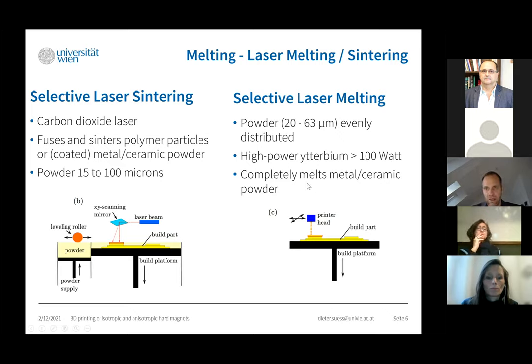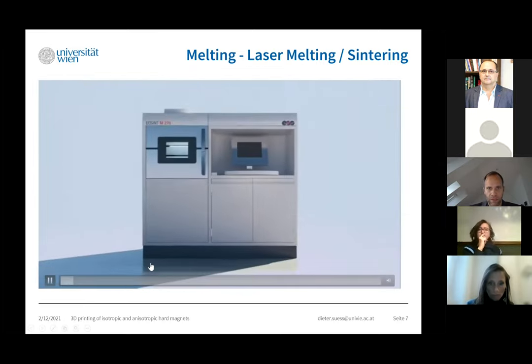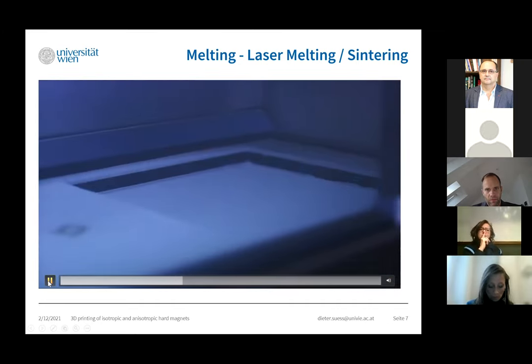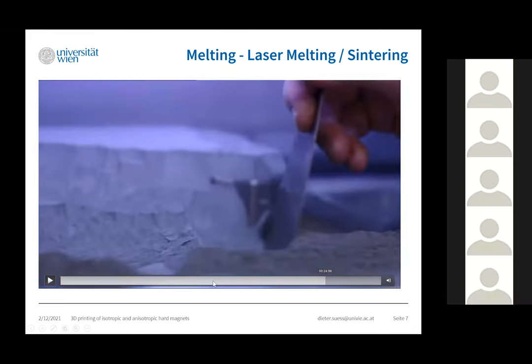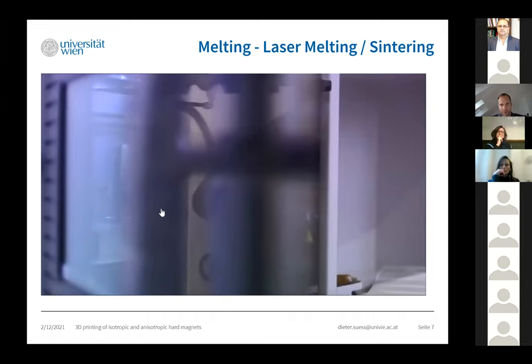If you do selective laser melting, you completely melt the entire structure. And this was also nicely presented by Oliver Gutfleisch, that here also the existence of new phases can be realized, which gives a lot of additional flexibility and playground to this method. Of course, selective laser melting is a much more complicated technique. There you see that just in the parts where the laser hits the powder, you get the solid structure, and everything else is removed. The powder is removed and can be used again. These machines are, of course, much more expensive than fused filament fabrication printers, which can be purchased for 1,000 euros.